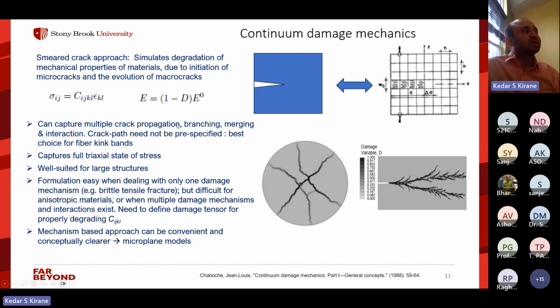Now, the benefits of this approach is that it can automatically capture initiation of cracks, propagation, branching, merging, interactions, and there have been several applications. I need not show it, but I have shown a couple of them here. And importantly, it can capture the complete triaxial state of stress. So you can have complicated constitutive models, and it merges well with this damage mechanics approach. And that is especially important for anisotropic materials when multiple damage mechanisms exist. But the challenge is you need to define the damage variable for each failure mode separately, and it leads to a damage tensor, and it becomes very phenomenological and complex. So often for composites, it has been discussed that an approach which handles individual mechanisms separately probably is more convenient, and it is more conceptually clear.